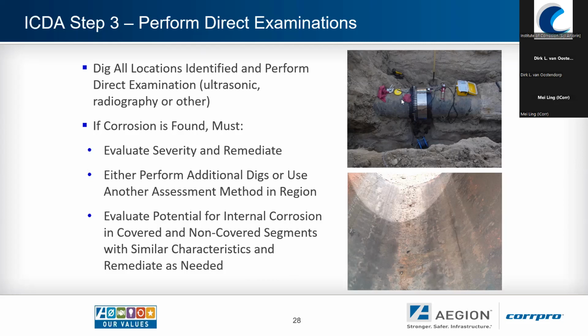So in the photo on the top right, there's a guided wave tool being installed on the pipeline to do the shots. In the bottom photo, this was in what the operator was convinced was a dry natural gas pipeline. Yet if we look closely, we can easily see the water tracks from where the water was flowing along the bottom of the pipeline. And at the very bottom, at the 6 o'clock location, there's plenty of corrosion with several very large metal loss pits in there.